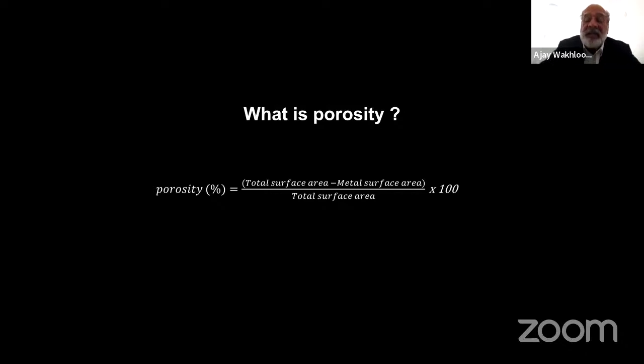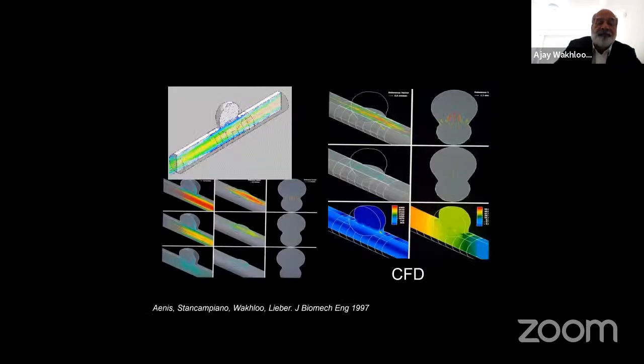Most of the brain stents that you use in your daily practice have a porosity somewhere around 84-85%. That means the metal amount is about 15%. Flow diverters on the other side have a porosity of 60-70%. And I'll explain shortly why that's the case. That means their metal amount is somewhere around 40-30%.